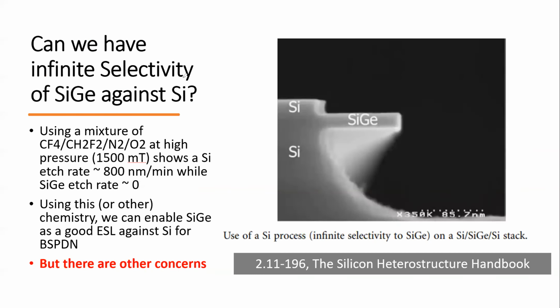Well, can we have infinite selectivity of SiGe against silicon? Well, yes, it's been done, I think in 2010 or 2016, I forgot, in this book. There's a process using this chemistry, CF4, CH2F2, N2, O2, at high pressure. So the silicon etch rate is very high, while the SiGe etch rate is almost zero. So they form this very clean shape. Here you etch silicon and leave SiGe behind. There's no touch. So you can imagine that people can perfect this recipe or a similar recipe to enable SiGe as a good stop layer against silicon for backside PDN.